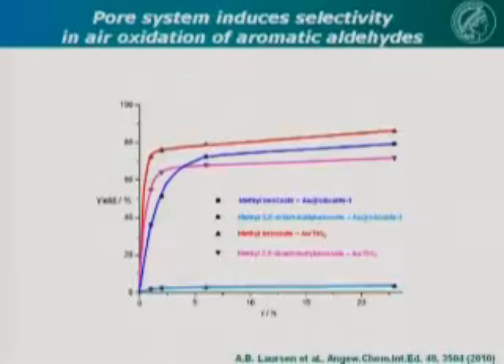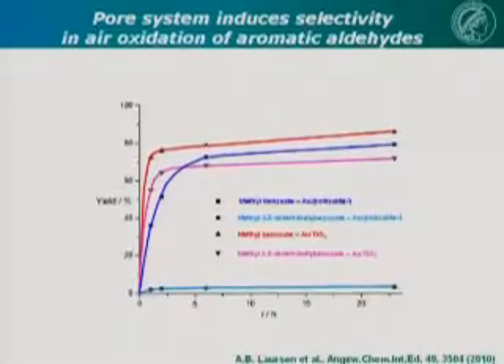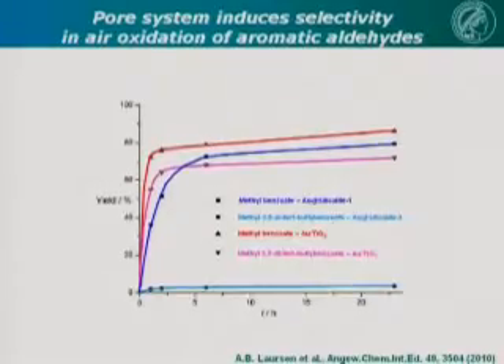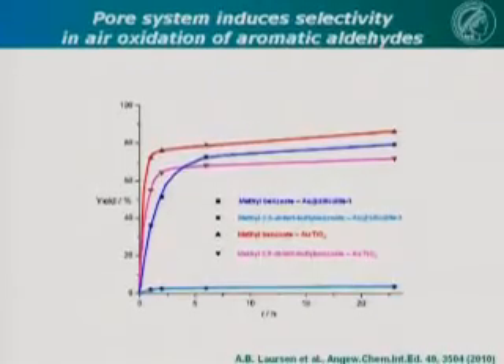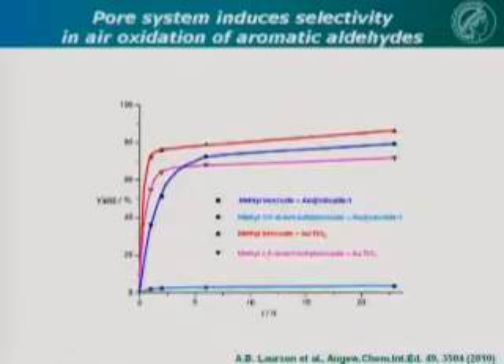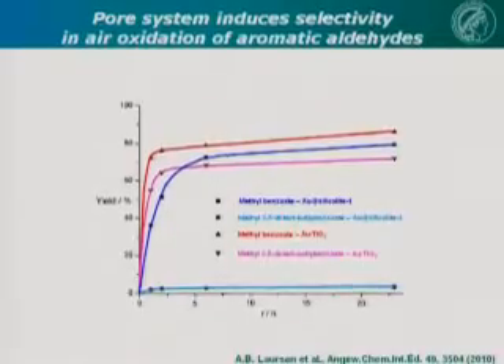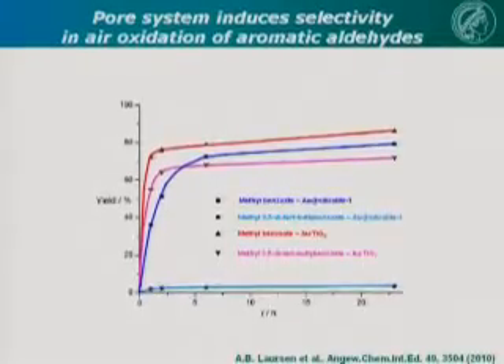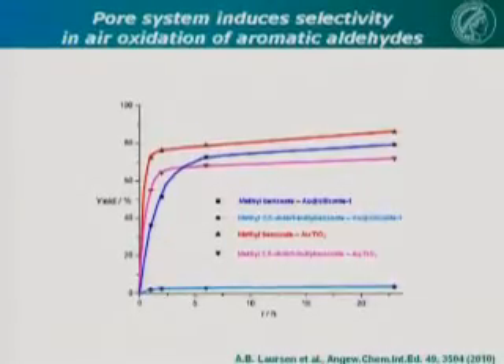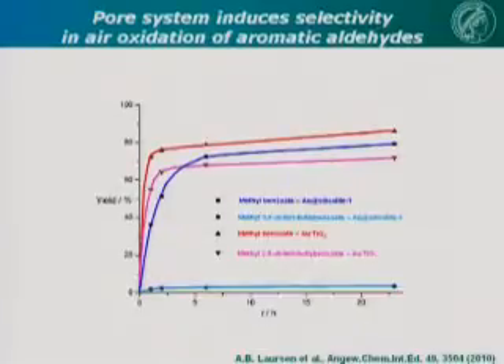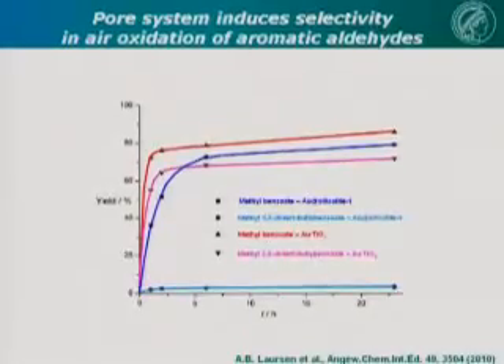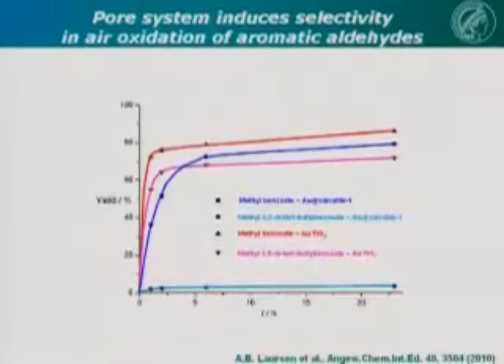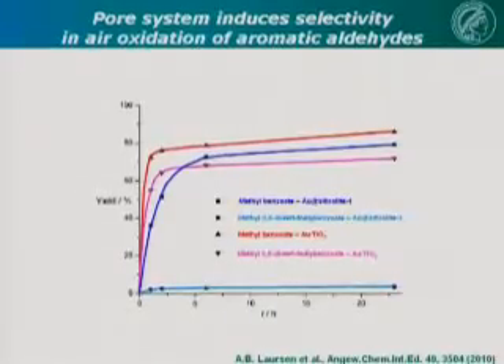The reference catalyst here is gold on titania, and we have looked at air oxidation of aromatic aldehydes, methyl benzoate, and then this very bulky methyl benzoate. If we don't have the gold in the pores of the zeolite, if they are just on titania, well, basically methyl benzoate and the bulky reference compound are converted at approximately the same level.